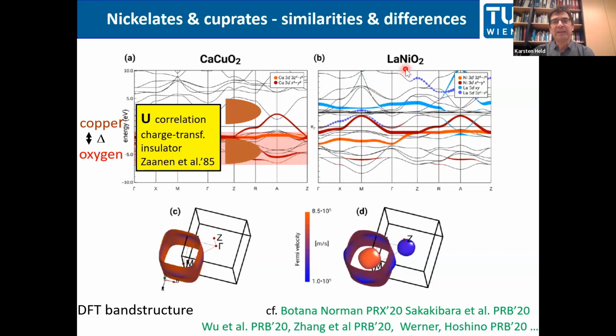Now, nickel is neighboring to copper in the periodic system. It's also +1. So in principle, this d x squared minus y squared orbital would just like to shift up. But the Fermi level, if you have it at the same position for cuprates and nickelates, still crosses this x squared minus y squared orbital. So if we fix the x squared minus y squared orbital via the Fermi level, everything else moves down. And that means that the oxygen bands are now far enough below the Fermi energy that the holes don't go in there.